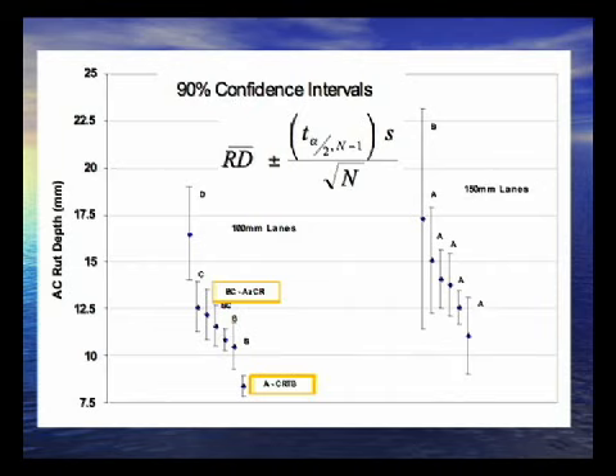So what we see here is for the thinner sections, there's some kind of a pecking order in terms of rutting. But this is using some statistical techniques to do clustered ranking. So this is what we see here. The terminal blend performing the best, the Arizona crumb rubber section next there. In the thicker lanes, it's a different story. But you know what? They're basically very similar in rutting. And I think, personally, in terms of the goals of the experiment, they're very similar, running from very similar PGs. So we'll get to the PG spec later. In terms of fatigue cracking, this is where we see really big differences between the performance of these materials. Rutting, not so much, but fatigue cracking, definitely yes.